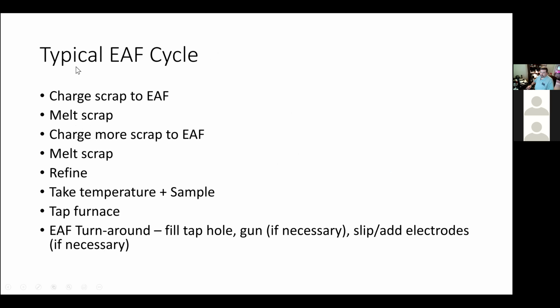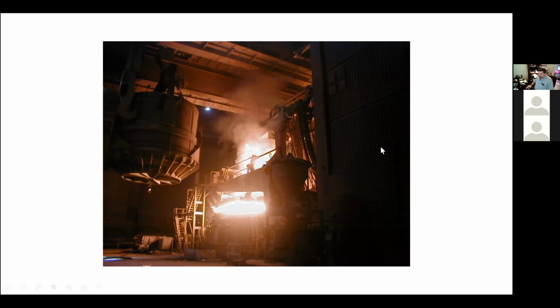So the EAF cycle, you typically charge scrap to the furnace, you melt it, then you might charge more scrap to the furnace and melt it, and then carry out what we call refining, which is blowing oxygen into it. Take a temperature and a sample to see if we're where we want to be. And then we tap the furnace, and then we turn it around. So we might have to adjust our electrodes and so forth.